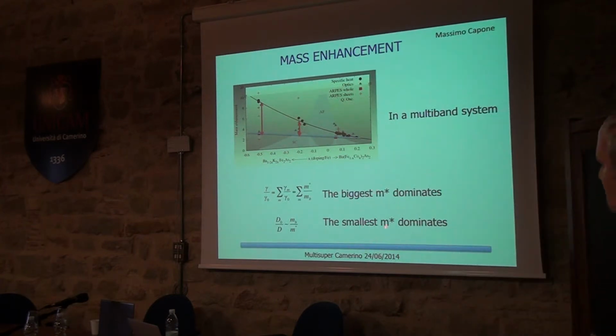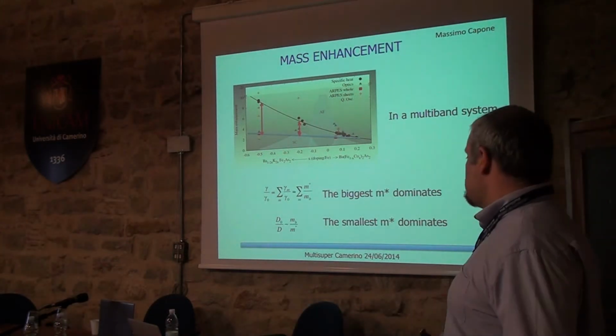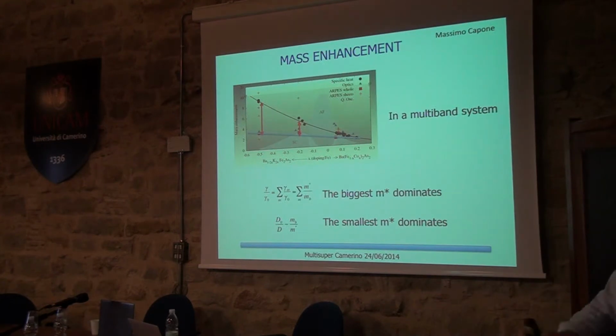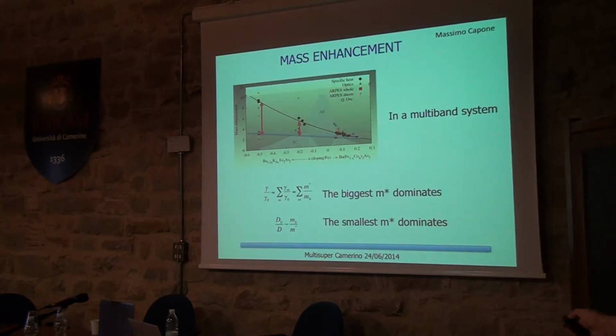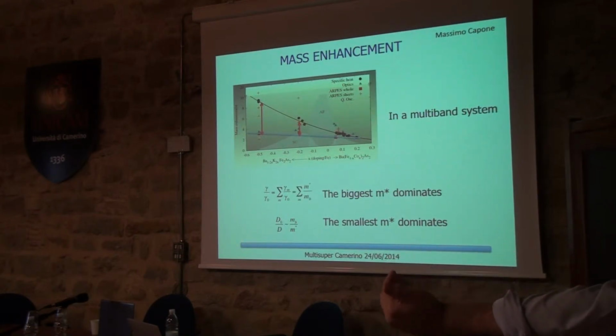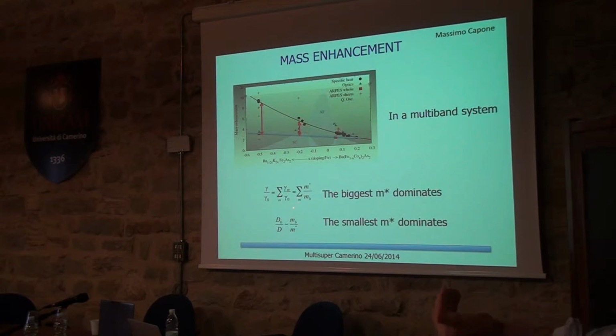Let me also mention why we have this. We now interpret all this in terms of a collection of many carriers with different effective masses. Essentially, in the specific heat, you have a sum of specific heats for the different carriers. So you sum up essentially the m stars. So if there is a spread, the biggest one is the one that matters. While in the optical conductivity, the effective mass is in the denominator of any estimate of the Drude weight. So it's something where the light carriers matter.